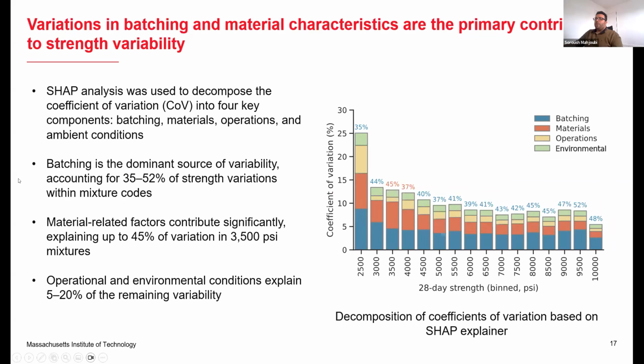We were also able to decompose the coefficient of variation using the SHAP explainer, and we found that we can basically categorize these variables into batching, materials, operations, and environmental conditions. And we found that the batching variation is the dominant source of variability and can explain about 40 to 50% of strength variations within the mix codes, and material-related variations also explain about 40% of the variations in the mix codes, and the rest goes to the operational variations, which is about 5 to 20%.